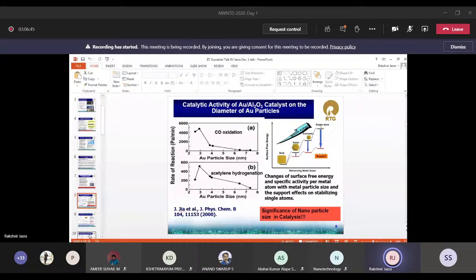So it means what? Normally we say any particle which is less than 100 nanometer is a nanoparticle. That is true. But to be catalytically active, it's not necessarily that when you go to 10 nanometer, 20 nanometer, it will become very active catalytically. You have to go to a specific size for a specific metal where it is showing maximum activity. For example, in this case gold, if you are at 3 to 4 nanometer size gold, then only you will see very good activity for carbon monoxide oxidation.